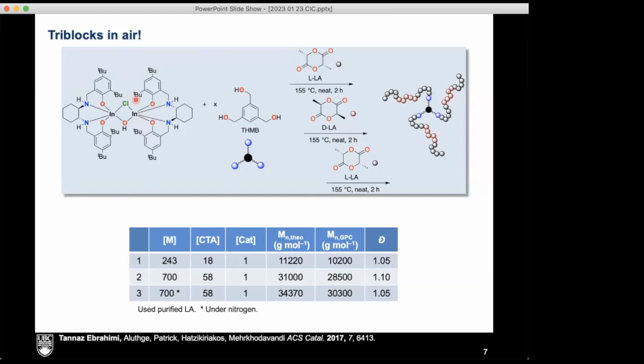This catalyst is a chlorohydroxy-bridged compound, which is completely air and moisture stable in Vancouver air. We can take this catalyst in neat lactide with a solid triol, so everything is under neat conditions, and in air, carry out very controlled polymerization of lactide. Here, I'm adding two different enantiomers of lactide, L and D lactide, and we were able to, in a very controlled fashion, generate these tri-armed polymers. What I love about this is no glove box necessary. This is all just done in a reactor in air. We just take it off after 2 hours, add more monomer, put on the lid, and away we go.